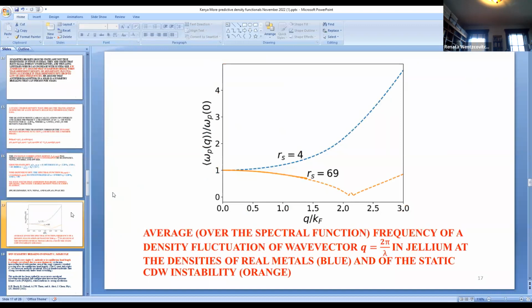On the horizontal axis, we have the wave vector of the density fluctuation Q divided by the Fermi wave vector Kf. On the vertical axis, we have an average plasma frequency as a function of Q, divided by the Q equals 0 plasma frequency of the metal, the uniform gas. This average plasma frequency is defined by averaging over the spectral function the frequency of the density fluctuation of wave vector Q equals 2 pi over lambda.